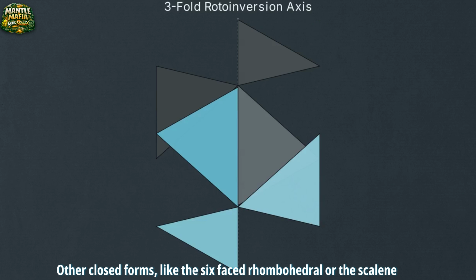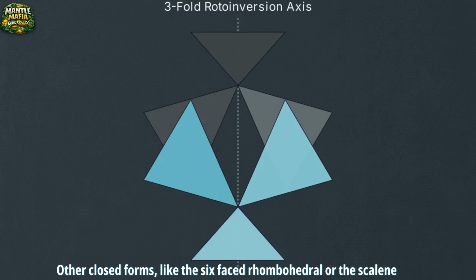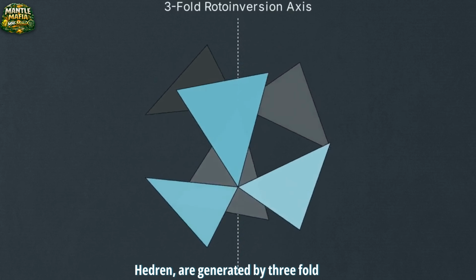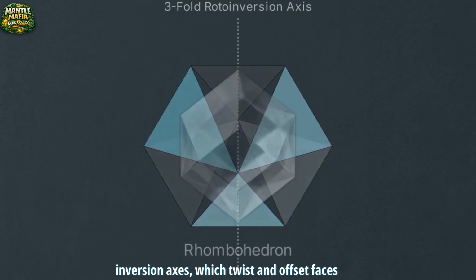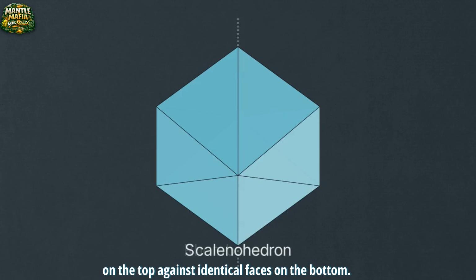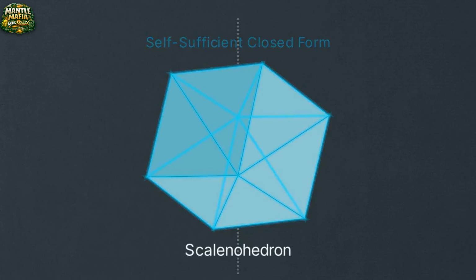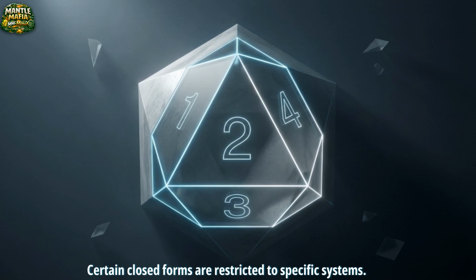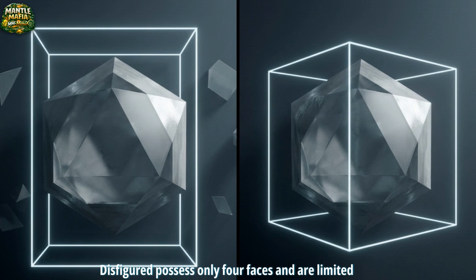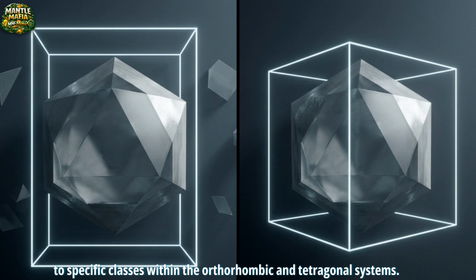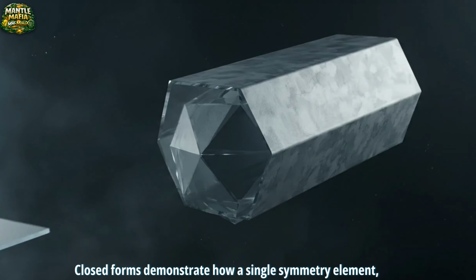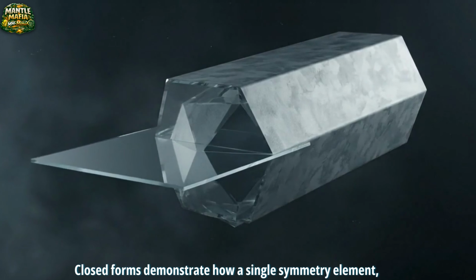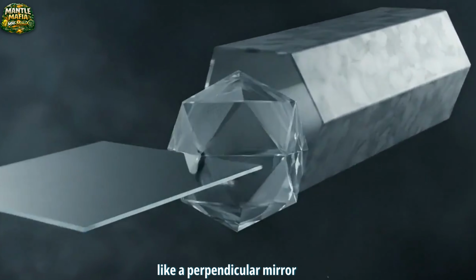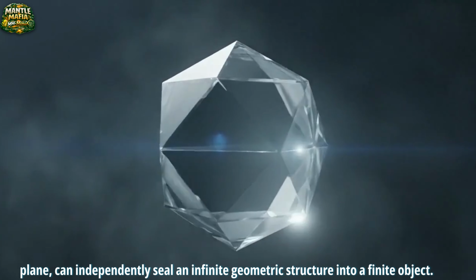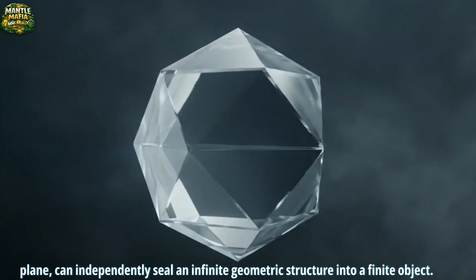Other closed forms, like the 6-faced rhombohedron or the scalenohedron, are generated by 3-fold roto-inversion axes, which twist and offset faces on the top against identical faces on the bottom. Certain closed forms are restricted to specific systems. Dysphenoids possess only 4 faces and are limited to specific classes within the orthorhombic and tetragonal systems. Closed forms demonstrate how a single symmetry element, like a perpendicular mirror plane, can independently seal an infinite geometric structure into a finite object.